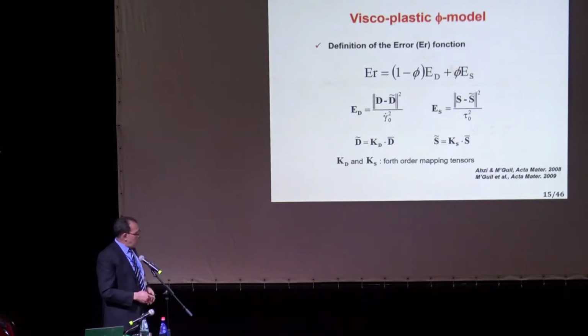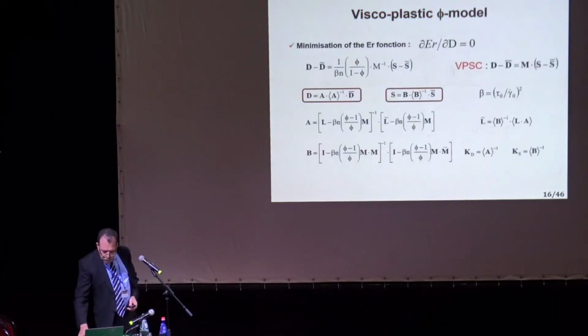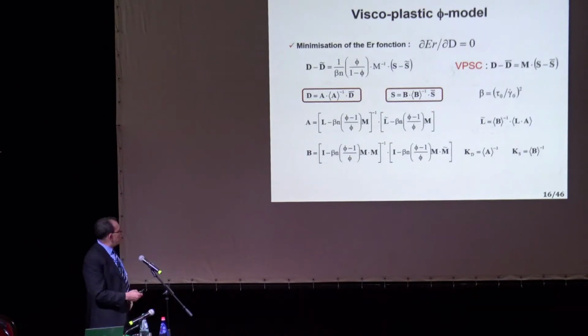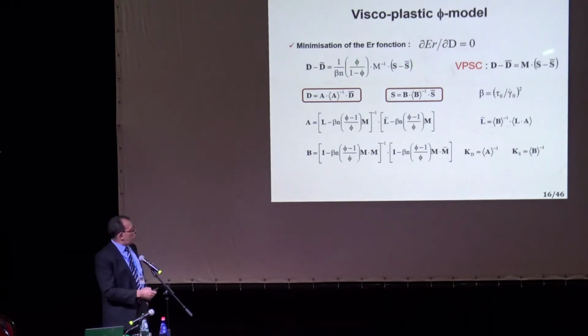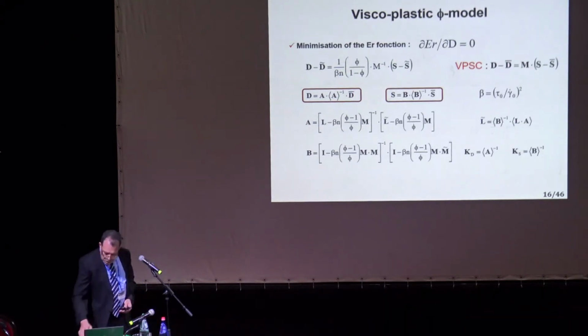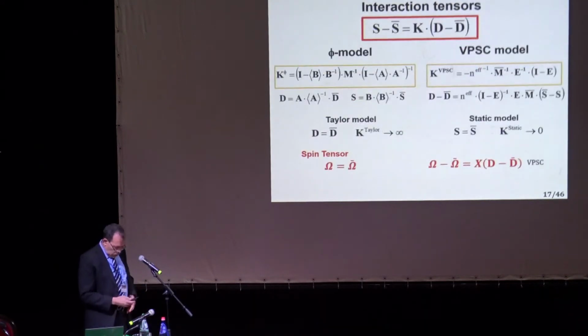So, by minimizing this error function, very simple, we end up with D minus D bar or D tilde equals this S minus S bar, similar to the viscoplastic self-consistent. Exactly the same type of writing. The only thing is here we have an, sorry, it should be R here. I made a mistake. It should be R. And this is a different R, in fact. This is a different interaction tensor. Okay? So I will not go through these details here. There is no need. Let me just go through this.